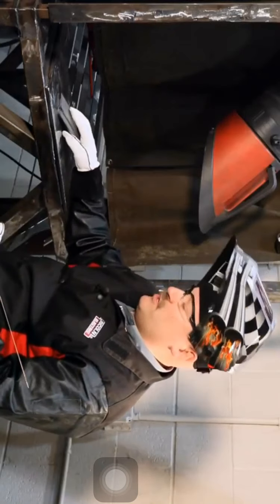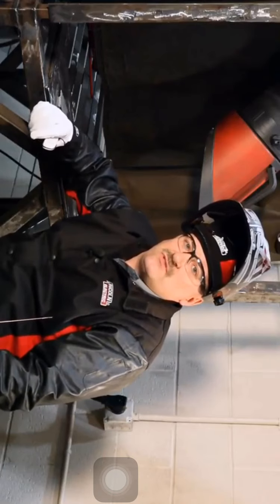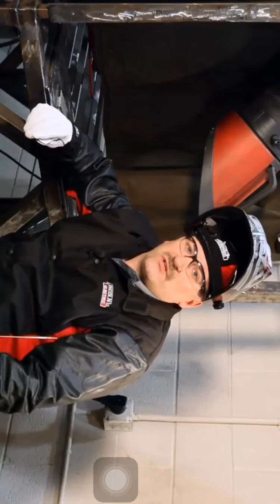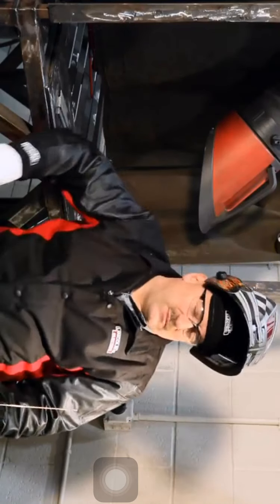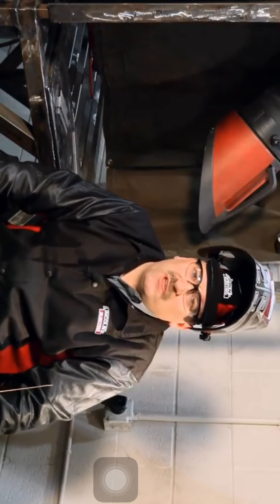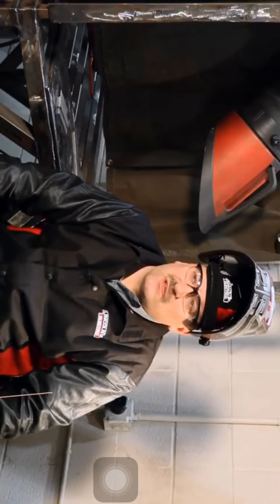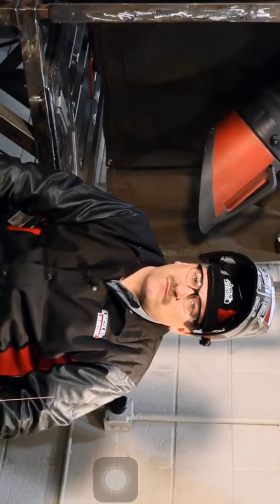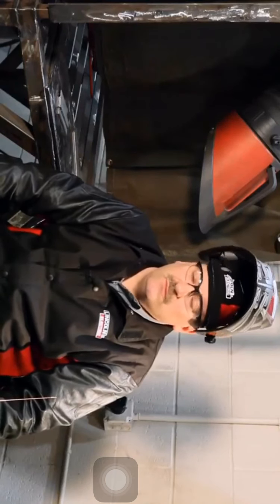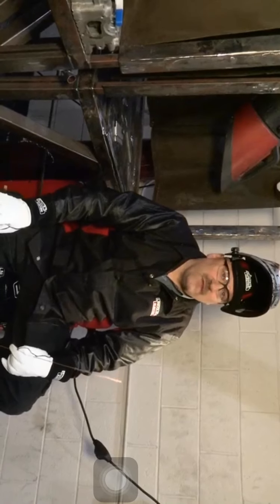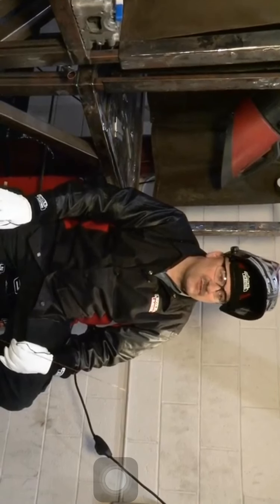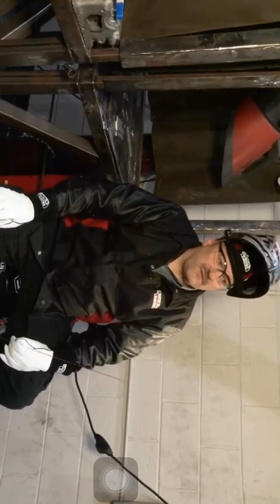We're going to be TIG welding this on DC negative polarity using argon gas, a 3/32, 2% ceriated tungsten. I'm going to be running about 120 amps, seeing as I have a 120 thousandths thick material. That's the optimum current for 120 thousandths material, 120 amps. I can run that at a higher current if I move faster. I can run it at a lower current if I move slower.